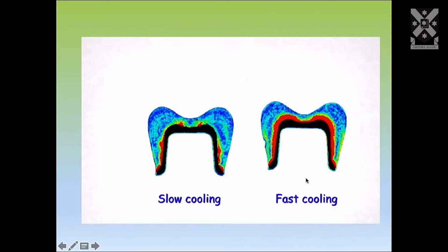And the result of that is that if you fast cool it, and all the manufacturers had a fast cooling cycle as part of their recommended procedure, what happens is the porcelain in the middle, which is still liquid, now cannot contract, and it sets up an area of tension inside the porcelain. And this was the cause of the cracking or the chipping that was taking place.